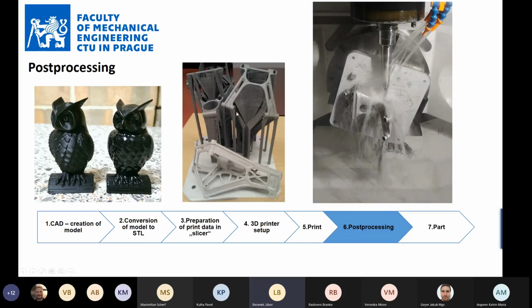So the part finishing or post-processing: this is how it comes from the printer. If the part is a very thin structure, topologically optimized, full of supports, and you design the supports so that they can be removed manually, then the operator can clean the part quite easily. But when the part should have better specifications, you are aiming for machining on a part whose deformations are half a millimeter or even bigger. In this case, this is a part for a military jet here in the Czech Republic. This is one of the projects, and the deformation of the part was bigger than 1 millimeter. So you have to use special techniques of programming the CMM machine, because you cannot use the CAD data, because the CAD data is quite different from the actual part that is printed.